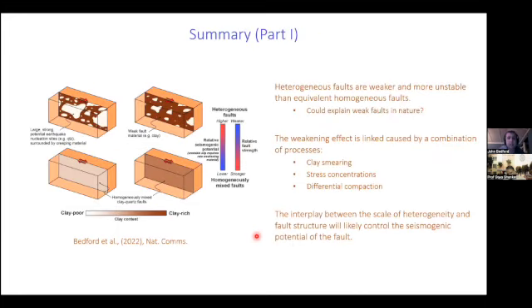But just to go back to the heterogeneous faults and to summarize this first part of the talk, we found that heterogeneous faults are weaker and also more unstable than mineralogically equivalent homogeneous faults. And therefore, this suggests that heterogeneity could contribute to fault weakness in nature. And the weakening effect is probably caused by a combination of mechanisms: some smearing of the weak phase, potentially stress concentrations caused by localization of the weak phase, and also competency contrasts leading to differential compaction and redistribution of normal stress along the fault. And at the large scale, the scale of heterogeneity is likely what's going to dictate whether you get patches large enough for earthquake nucleation or not.